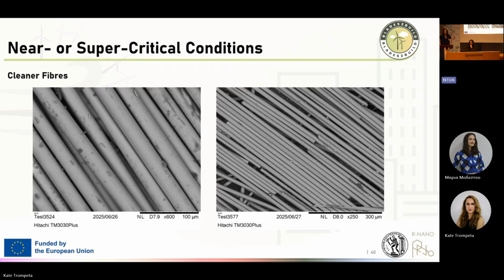However, we can see here that the difference between the fibers, the results through the supercritical solvolysis, is very obvious because we have much cleaner fibers, and fibers that are not degraded as much as in the low temperature solvolysis.